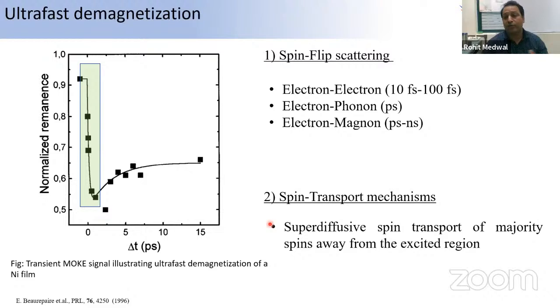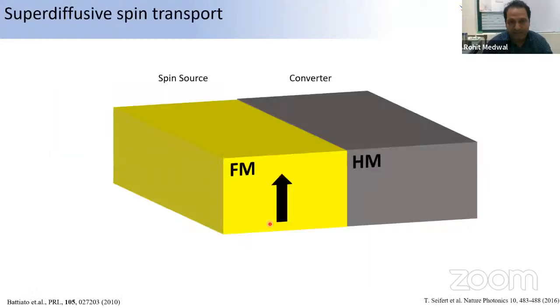People are also talking about super-diffusive spin transport, where they're saying that when you shine a light on the ferromagnetic materials, you can really allow the spins to go away from one area to another area. Because when you shine a light, these electrons are really hot electrons. They are really far above the excitation energy. They are above the Fermi level. They are really randomly scattering. As a result of this scattering, they try to move from one area to another area. So this effect is very dominant in the spin transport community. So I will explain in detail what I'm talking about in super-diffusive spin transport.